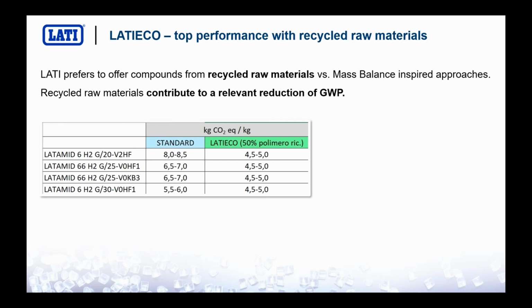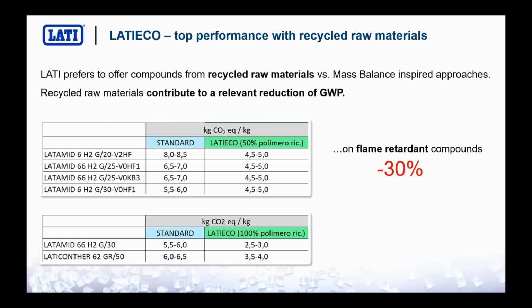If you compare the global warming potential of a standard product and its LATI Eco version, you will see that with flame retardants, you can reduce the global warming potential by 30%. And if you check the LATI Eco version of the engineering products, the glass fiber filled materials like nylon 6 or nylon 6,6, you see that this percentage can increase up to 50%. So by introducing recycled polymers, you can reduce the global warming potential of a flame retardant compound by 30%, and that of engineering compounds by up to 50%. And this gives you exactly an idea of how important it is to use really recycled polymers in new compounds.